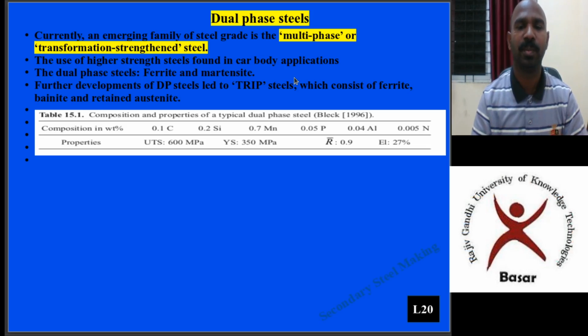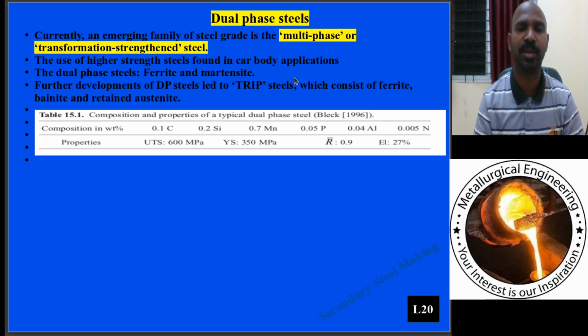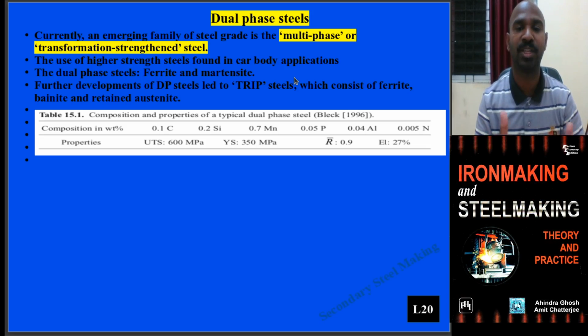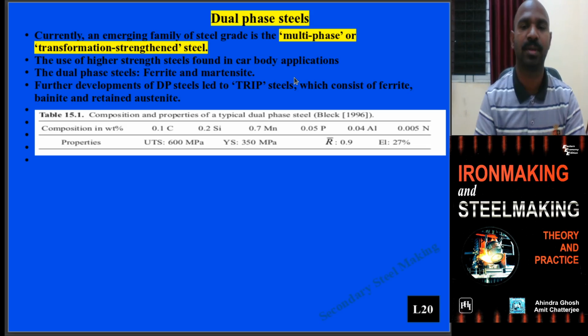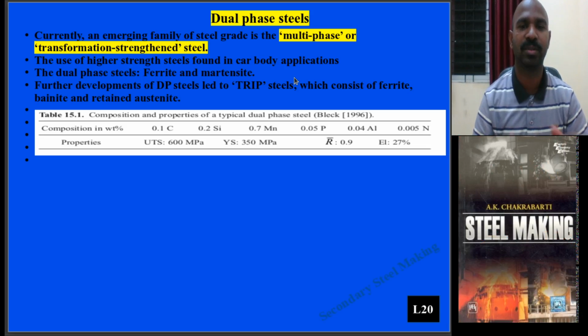That particular phase is constant and cooled, so that you by choosing the TTT curve route, converting into the bainite. But also some amount of austenite is retaining, which is called retained austenite. The TRIP steel is nothing but ferrite, bainite plus retained austenite.